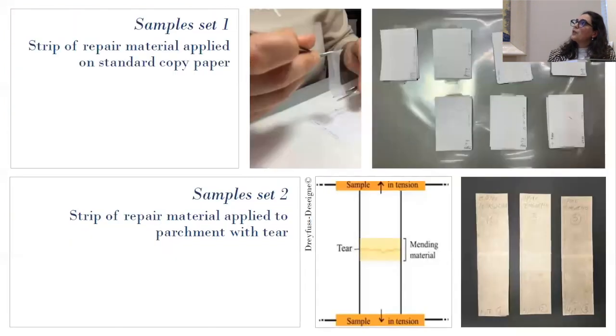Next slide, please. So, we created two different sets of samples. With the first set of samples, what we wanted to test was only the proper reactivation of the adhesive. In this case, we just cut strips of our mending material, pre-coated with the different adhesives, and reactivated them according to the three different methods that I showed you, and then we laid them on a piece of standard copy paper, because with this set of samples we wanted to test if the adhesive was reactivated 100%. With the second set of samples, what we wanted to test was the reactivation of our repair material on parchment. So we cut strips of parchment. The parchment was selected because its appearance was similar to the parchment support that we had, and we created tears that were mended with different combinations.